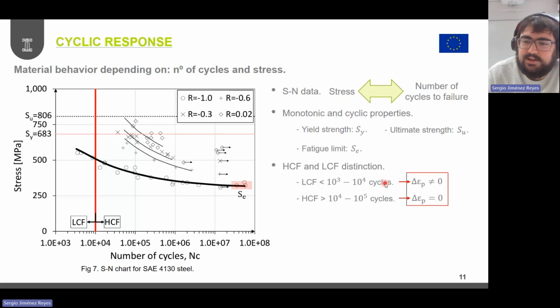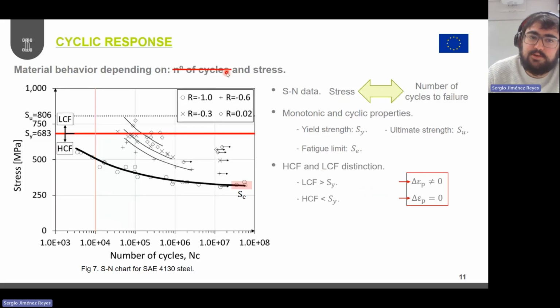What is interesting is realizing that these low cycle fatigue scenarios take place with the presence of plastic strain accumulation, while in the high cycle fatigue cases, no plastic strain accumulation takes place. So we can somehow relate this with what we've seen previously for the monotonic scenarios. And so instead of focusing on the result, the number of cycles, we can forget about the number of cycles in the fatigue characterization and just focus on the stress being applied on our material. Because if we want to experience plastic strains, then we should go above the yield strength of the material. And the opposite can also be applied for the high cycle fatigue condition.